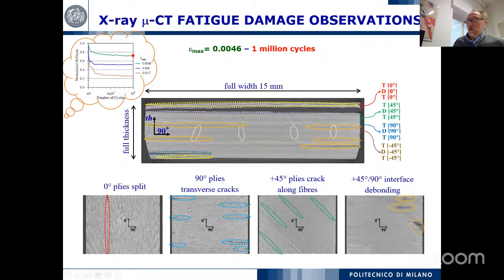The main damage mode observed after 1 million cycles, as mentioned, is splitting in the zero ply. So you have transverse cracks that mainly start from the edge. This is almost standard, and you also have cracks along the fiber in the 45 ply and starting delamination. The delamination mainly happens at the interface between the 45 and 90 degree plies. This is what we have seen in the experimental tests with different loading conditions and different laminates.